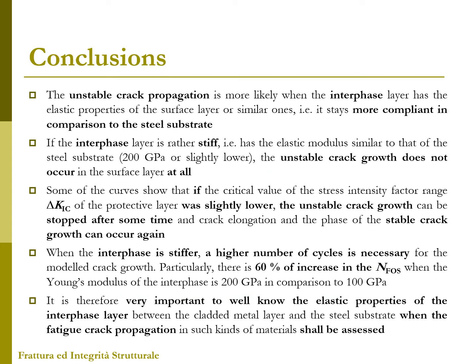From the results presented, it can be concluded that unstable crack propagation is more likely when the interphase layer is more compliant in comparison to the steel substrate. It is shown that if delta K1C was slightly lower, the unstable crack growth can be stopped after some time and the stable crack growth can occur again. When the interphase is stiffer, for instance 200 gigapascals in comparison to 100 gigapascals, there is a 60% increase in the number of cycles to failure.